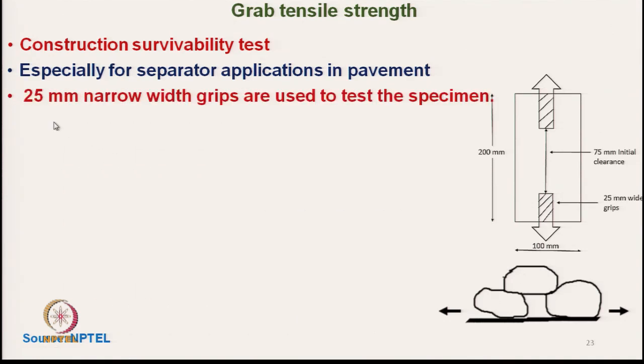The 25 millimeter narrow width grips are used here. So, the width of the grips is 25 millimeter and width of the specimen here is 100 millimeter.